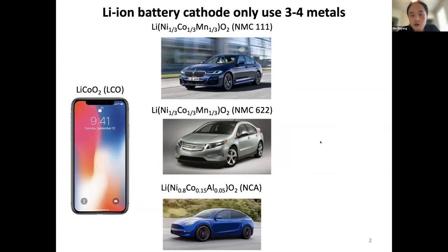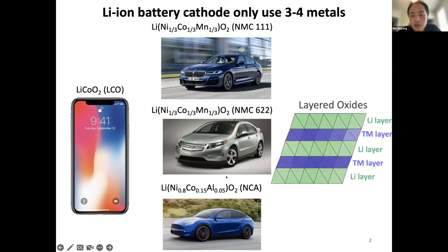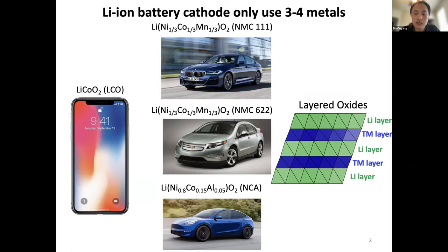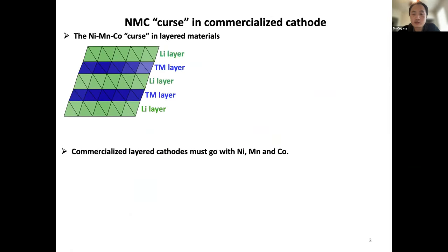We call them NMC, or in Tesla we're using NCA material. All of them actually use only three to four metals and they take the same structure, called the layered oxide structure, where you have alternation of a lithium layer and a transition metal layer. It's kind of funny — so many people are working on battery materials, but we realized only three to four metals can work as active cathode material. We joke about something called the NMC curse.